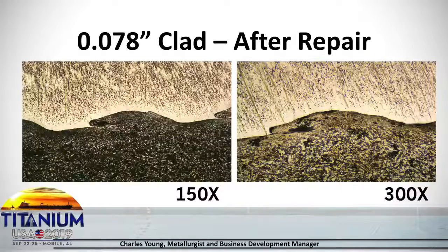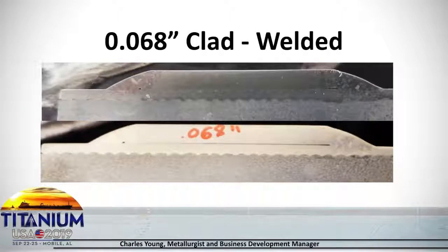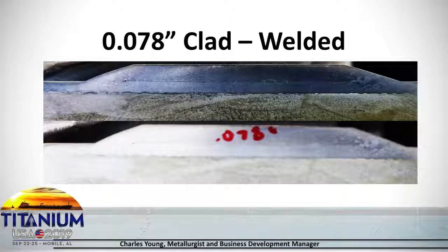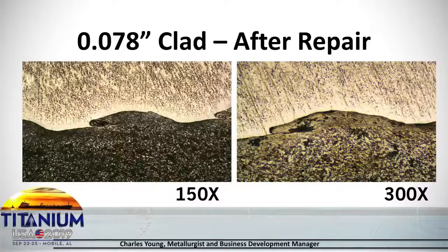At 0.078 inches, again, you can see the weld here. You see a little bit of discoloration here, a little bit of discoloration here, but nothing to be concerned about. You still have very good bond strength there, and if you look at it under a microscope, again, you see nothing out of the ordinary. It's basically the bond you would have for an explosive bonded piece of material.